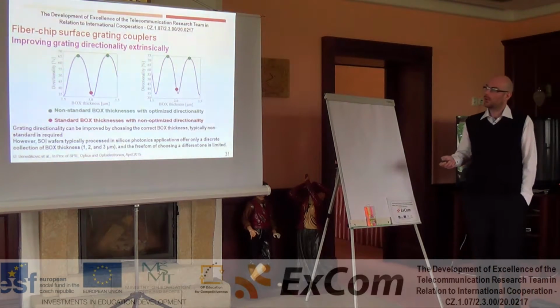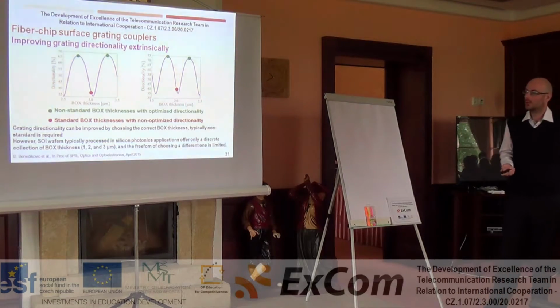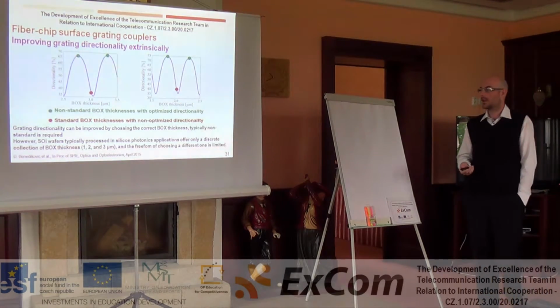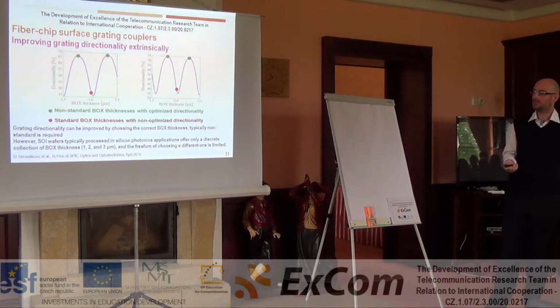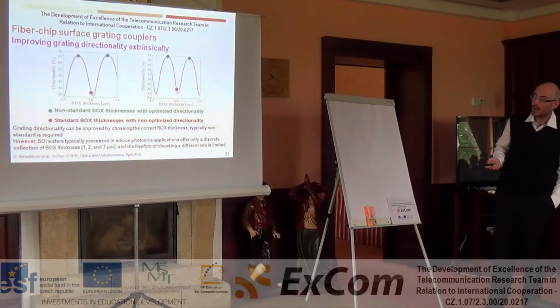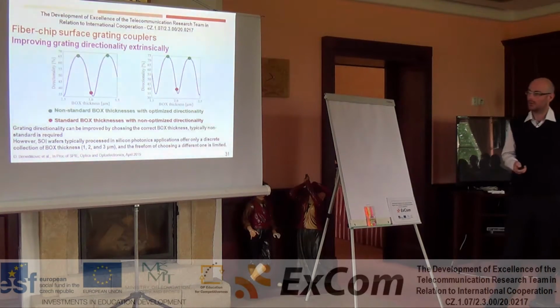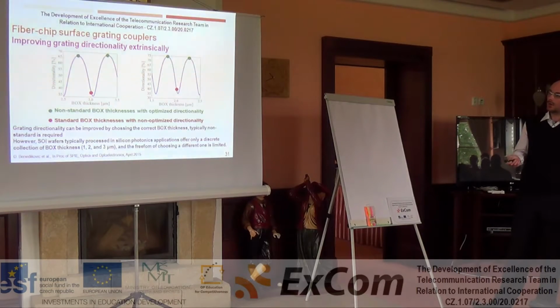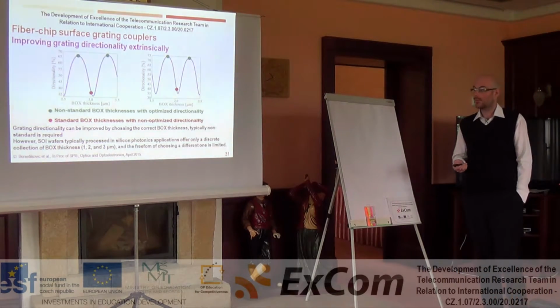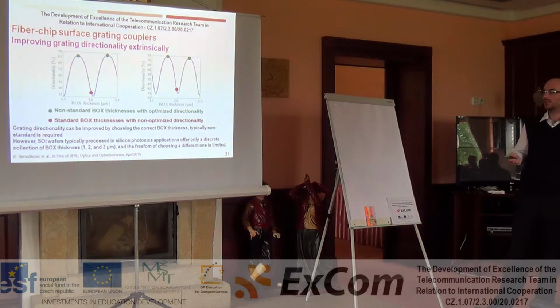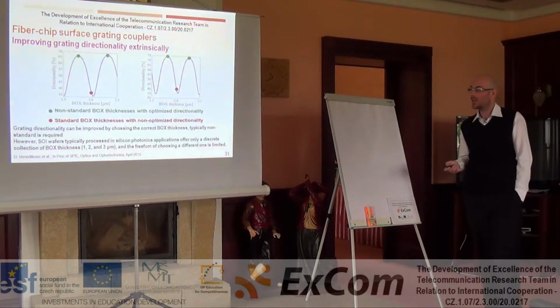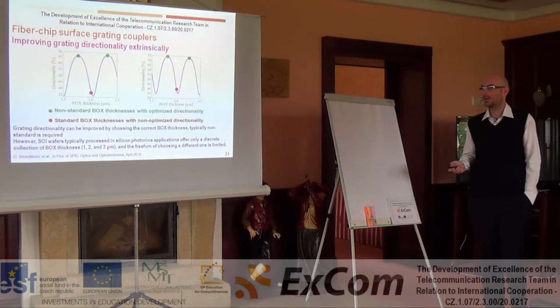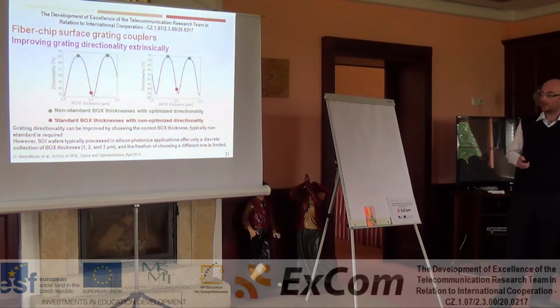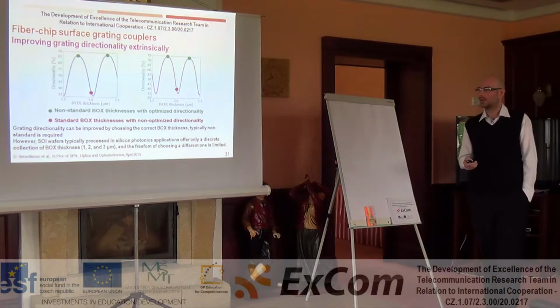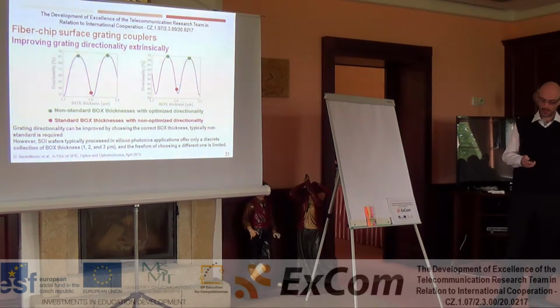By choosing the proper thickness of this box layer, we can directly improve the grating directionality, but at the expense of requiring non-standard silicon on insulator wafers. However, typical silicon on insulator wafers that are processed in silicon photonics applications offer only a discrete collection of box thicknesses, typically 1 micrometer, 2 micrometer, or 3 micrometer, and the freedom of choosing a different one is very limited.